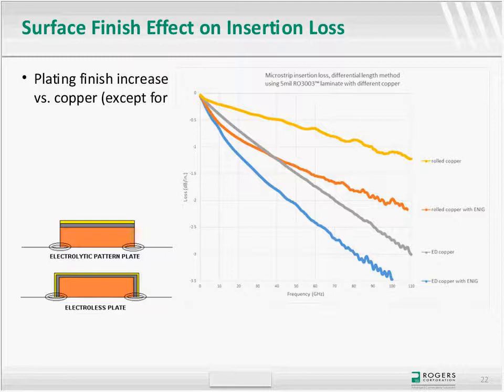And what I would say is important to remember here is not only the copper foil, but also the plating selection. We have found in the past that when you're doing a plating process on a microstrip circuit, the way traditional circuits are made, the plating goes on the surface and on the sides as well. This is the traditional electroless process, in many chemistries, versus the electrolytic. Electrolytic is typically done on the very top surface before the copper is etched. This layer is then used as a copper resist when you're etching.